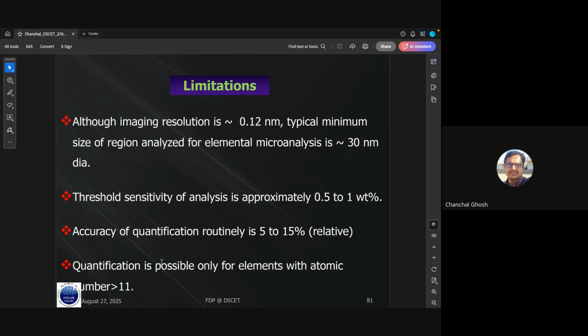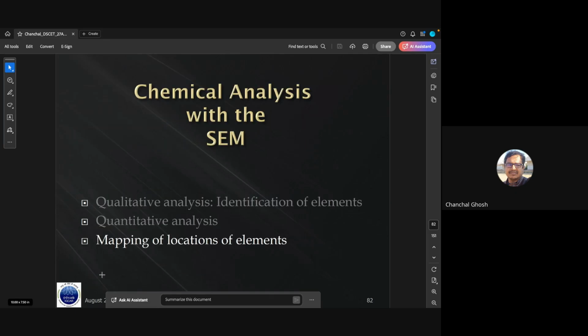And for EDS, one more important piece of information is that quantification is possible only for elements with Z higher than 11, for higher Z number. It is not that X-rays are not generated for the low atomic number elements like hydrogen, carbon, oxygen. They are generated, but while traversing, most of the time they get absorbed, and they may not even come out from the material.